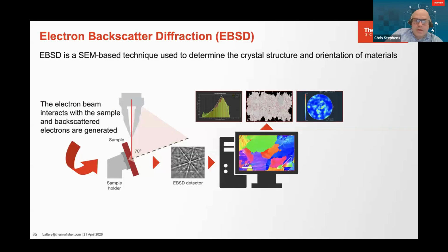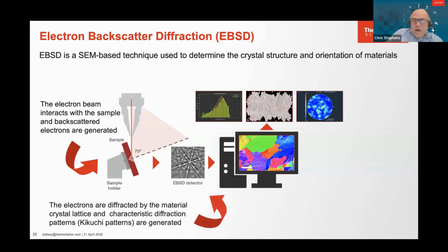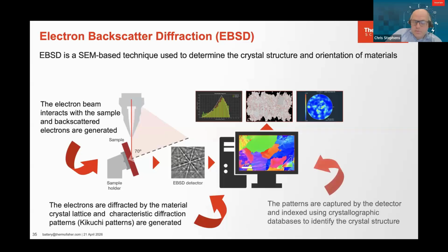To do this with the EBSD technique, typically you would tilt the sample. And what happens is, as the electron beam interacts with the sample, a proportion of this signal will be coherent. Because of this, you'll get a diffraction pattern, and the software is able to automatically identify or solve that diffraction pattern, work out the orientation, and then go on to the next point, the next point, the next point, to build up a map within the image. And because you're doing this, again, often many thousands of times a second, in a few minutes you're able to build up quite a detailed map that tells you the full structural information.